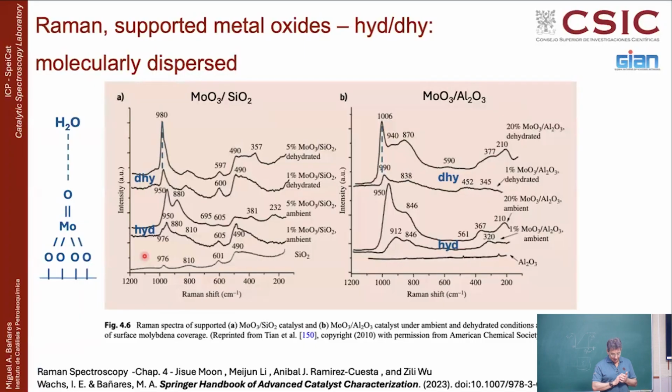Fine. Similarly, if instead of vanadium you are looking at molybdenum, it is a very similar story. Here you have ambient hydrated samples at 1 and 5 weight percent, and the same samples dehydrated at 1 and 5 weight percent. You see that hydrated looks very different than dehydrated. In the hydrated with low loading, it has this band. Hydrated with high loading, it has even more bands,